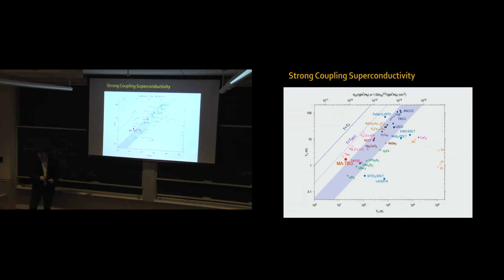It's like bound here, really bound. This means that we are pretty close to the BEC-BCS crossover, relatively close. We're not there yet, but compared to other systems, we're among the closest to that position in an electronic system. The only other system which has a little bit bigger coupling is iron selenide monolayer on STO, which is also an ultra strong coupling superconductor. It has very high TC for the density of electrons that they have.